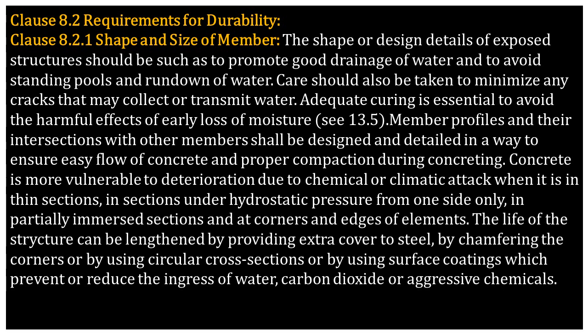Clause 8.2, Requirements for Durability. As I showed in my flow chart, this clause has 8 subclauses, from 8.2.1 to 8.2.8. Clause 8.2.1, Shape and size of member. The shape or design details of exposed structures should be such as to promote good drainage of water and to avoid standing pools and rundown of water. Care should also be taken to minimize any cracks that may collect or transmit water. Adequate curing is essential to avoid the harmful effects of early loss of moisture.